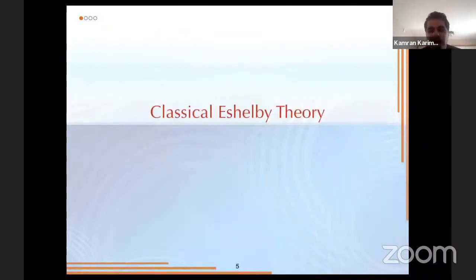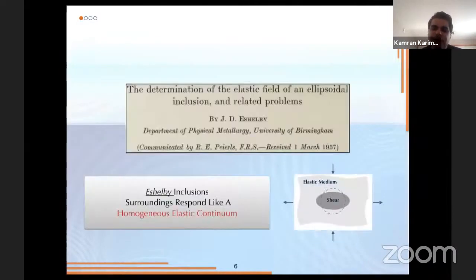So let me start with some background on the Eshelby theory, a seminal work by J.D. Eshelby in the late 50s. So the picture is that for an elastic medium with a soft inclusion within the matrix, under the load, the inclusion can go through this shear transformation. And since it is soft, you can imagine that if it is too soft, it's as if there is a hole within the elastic medium. So the stress tends to concentrate near this soft inclusion. It tends to decay as you get further away from the inclusion.